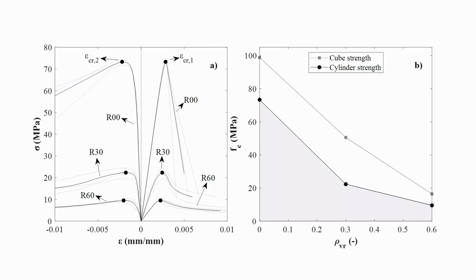And these are just the material properties. So for the infill concrete, these are the stress-strain curves and strengths. The R0 specimens had a 28-day strength of about 72 megapascals. The R30 concrete was just over 20 megapascals in strength, and the R60 concrete was about 10 megapascals.